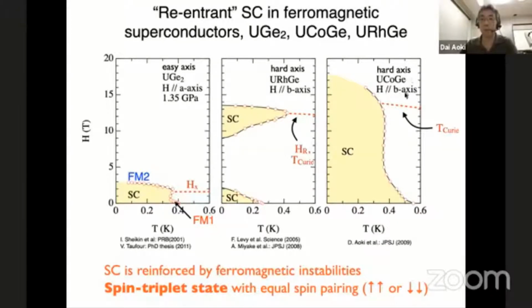So we studied this material also, and we found this kind of field-reinforced superconductivity, like an S shape. This unusual Hc2 curve cannot be explained by the conventional spin singlet state, so we can believe that the spin triplet state is realized with equal spin pairing. Because of equal spin pairing, there is no Pauli limitation, so we can expect a very large upper critical field.